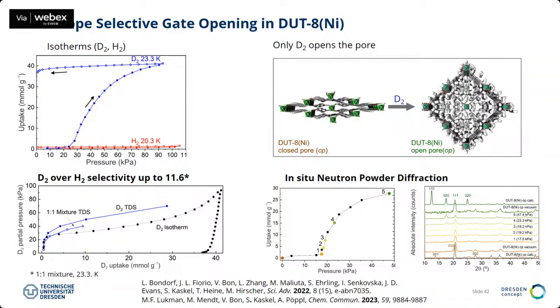So you see the pores have a huge uptake. 35 millimole per gram is really a lot at 23 Kelvin. And you see the characteristic hysteresis, while the hydrogen shows no uptake at all. These are the single component isotherms. And in a mixture experiment with a 1-to-1 mixture, in cooperation with Michael Hirscher in Stuttgart, we measured a selectivity value up to 11. So that's also quite good selectivity at these high loadings.